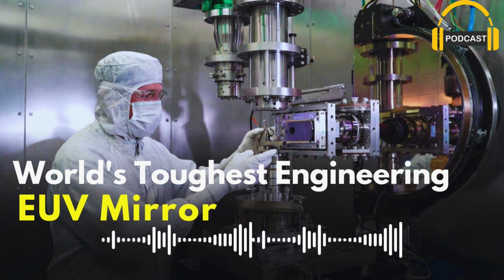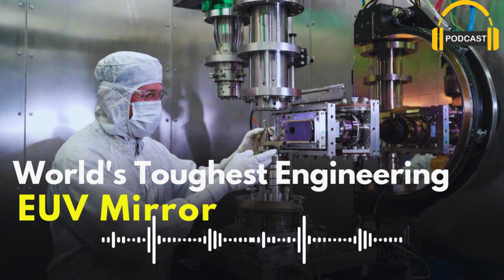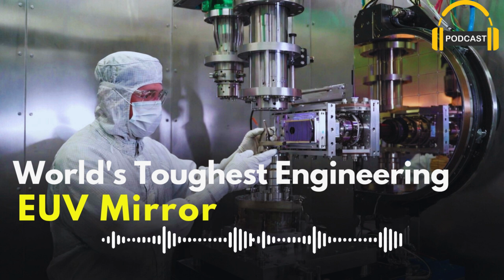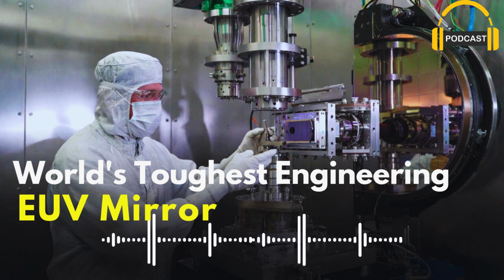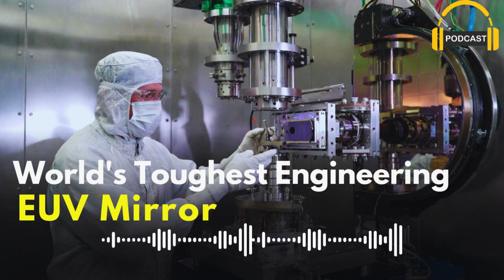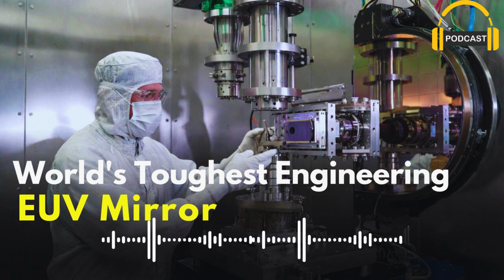It's a story of international teamwork, insane precision, and never giving up when almost everyone said it was impossible. By around 2010-2011, the mirrors were finally good enough. Zeiss had nailed the multi-layer deposition, the ultra-precise polishing, the ion beam figuring, and the picometer level metrology. Wavefront errors were down to the required fractions of a wavelength. In theory, you could project patterns smaller than 10 nanometers with almost no blur.